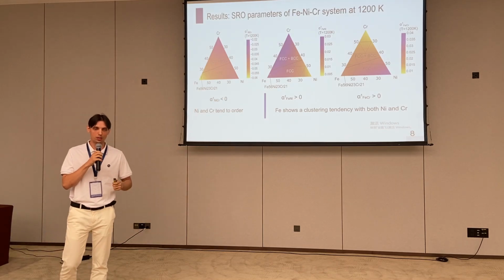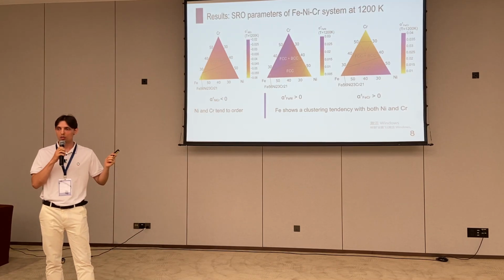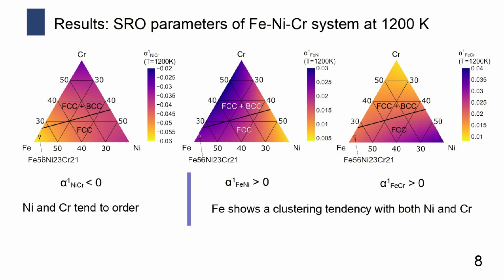Then we calculated the ternary maps for each pair of atoms. The short-range order parameter for the nickel-chromium pair in the whole composition space has a negative value. That means that nickel and chromium tend to order in this system, while iron-containing pairs like iron-nickel and iron-chromium have a positive short-range order parameter, meaning that they tend to clusterize.